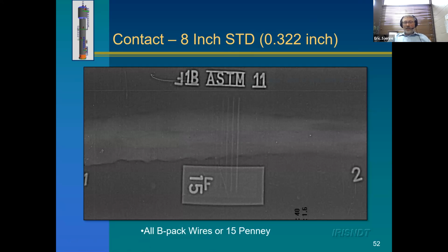So this is a weld inspection. In this case, this is the base plate of the weld. And this is an 8-inch standard pipe, so 8 inches in diameter and 0.322 inches thick. So in this case, this is the base material. We have a weld reinforcement on the outside of the pipe, but we also have a weld reinforcement on the inside. So this here is the weld reinforcement on the outside. And then this is where there's a double weld reinforcement for the radiograph. So that's where we see the outside weld reinforcement and the inside together.